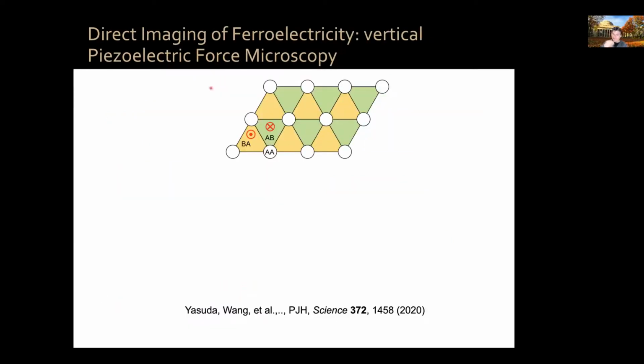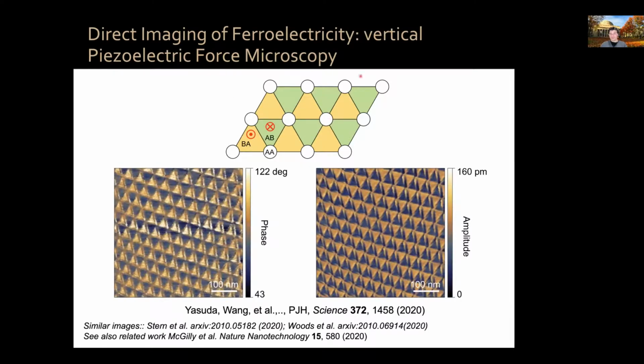Now, do we have direct imaging evidence of this moiré ferroelectricity? Indeed, we can do vertical piezoelectric force microscopy to look at this moiré ferroelectricity. And in fact, if you look with vertical piezoelectric force microscopy, you can see both in the phase and in the amplitude images this beautiful moiré pattern, this beautiful honeycomb moiré pattern, which you can lay on top of here, and you can see this moiré ferroelectricity. And I should mention that similar work was also obtained by two other groups, and related work a little bit earlier at Columbia University.